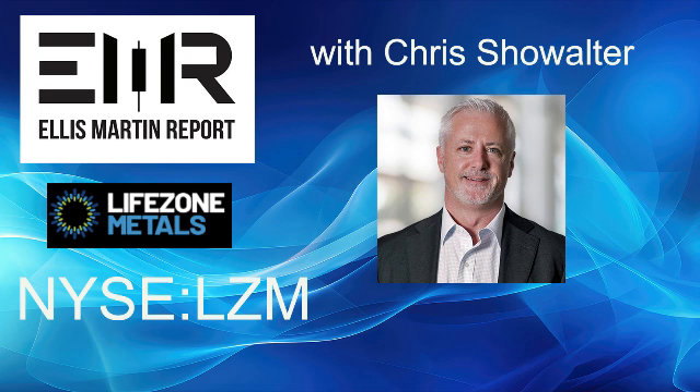Your recovery percentage is about 87.2% for nickel and about 85% for copper, which is really good. The Kabanga deposit is a very easily floatable material — there aren't any deleterious elements that you would normally encounter. HydroMet is a lot more forgiving; for instance, the MgO content in the ore body we're able to process, whereas previous owners intending to use a smelter did not incorporate the MgO as part of their plans. So we can capture a lot more tonnage. We will be getting to final nickel cathode, copper cathode, and cobalt rounds — 99.9 LME-grade metals. A full mine-to-final-refined vertically integrated project in Tanzania.